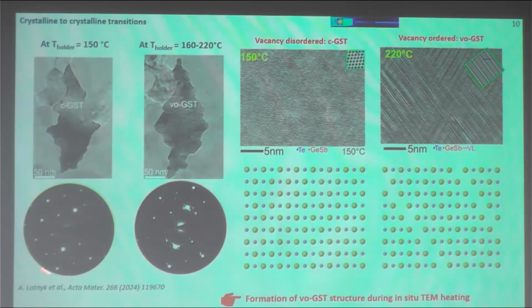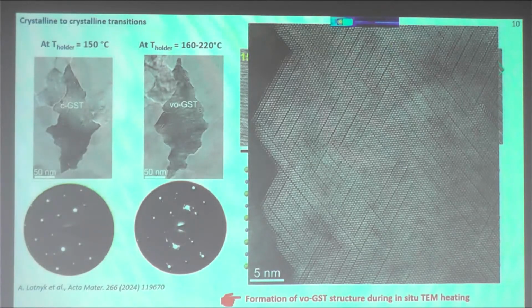Here, this is the cubic lattice. It's highly ordered here. It is like a single crystal. We see main reflections coming from the structure, and in the vacancy ordered structure, we see additional reflections which lie on the 111 planes. So these vacancy layers are formed on 111 planes in the cubic lattice. This can also be nicely seen in the HAADF image. As I said, it's a more convenient method to observe the real crystal structure. And this is again this large grain. It transformed to this vacancy ordered phase, and these dark lines in this image represent vacancies which are formed on the 111 plane, and then this is another 111 plane in the cubic lattice.